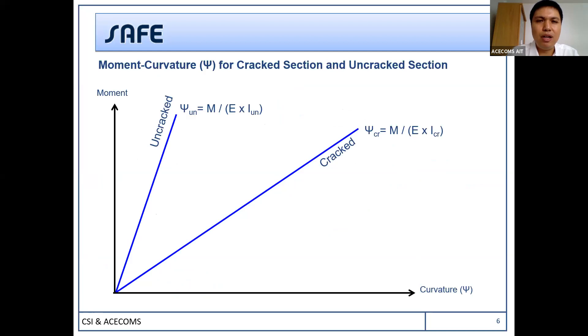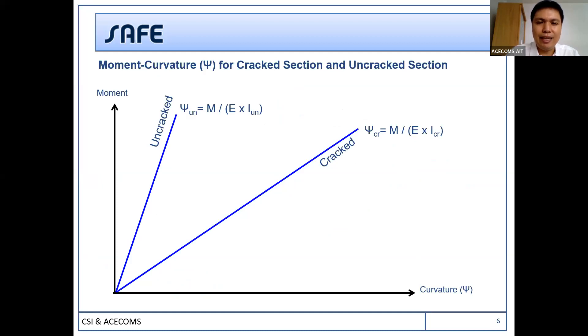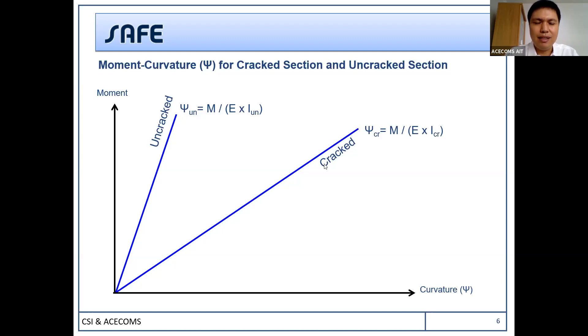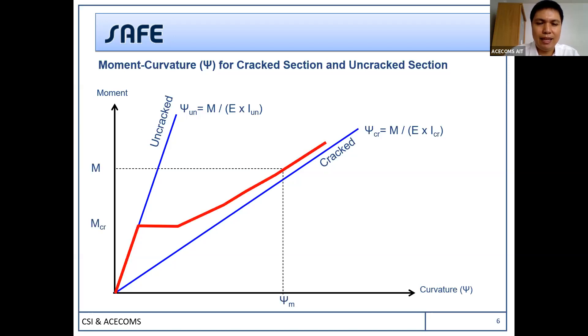From this, you can plot the moment-curvature relationship — it's like a stress-strain diagram or force and displacement. If concrete can support tension with no limit, you get the uncracked line. If concrete cannot support any tensile force, you get the fully cracked line. However, the real behavior is in between. Before the cracking moment, the curvature follows the uncracked line. After that, it shifts but not fully to the cracked line — there remains some tension stiffening shown by the red line.